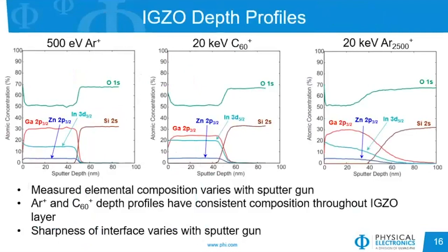Another material system that we have done a comparison on is IGZO, which is an indium gallium zinc oxide. This has multiple components. And we have also done a similar analysis using 500 eV argon, 20 keV C60+ and a 20 keV Ar2500+ cluster size. We can see several differences between these profiles related to the stoichiometry of the film. For example, in the first two plots you see a difference in the indium concentration. We can also look at the quality of the interface going from the IGZO material to the substrate, whereas it is quite sharp for the monoatomic argon and slightly less so, but good for the C60. However, the argon gas cluster shows very broad interfaces. And so we'd like to investigate that in a little more detail.